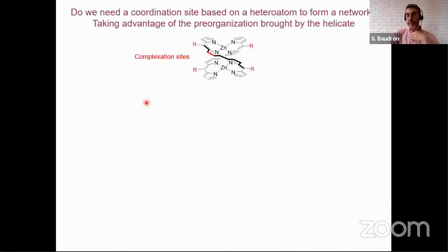So it's interesting to note that actually it is the complexation of the bis-dipyrrin to the zinc 2 cation that pre-organizes the 2 tetrapyrrolic strands around the metal centers and organizes them with respect to one another for subsequent complexation of silver 1 cations. It's also interesting to point out that not only do we organize the pyrrolic system in this case, but also the peripheral coordinating unit represented here by the R groups.